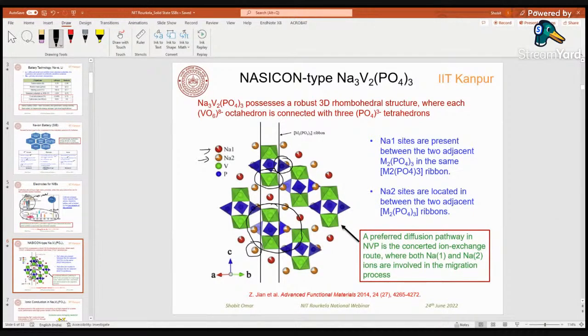Also, the diffusion mechanism involves both Na1 and Na2, and it is called a concerted ion exchange diffusion process. What do you mean by concerted ion exchange process? It means that two sodium ions are going to jump at the same time rather than one single jump occurring, right? So it requires a vacancy. The jump will only occur when two sodium ions are moving at the same time. So that's how the diffusion occurs in this type of process.